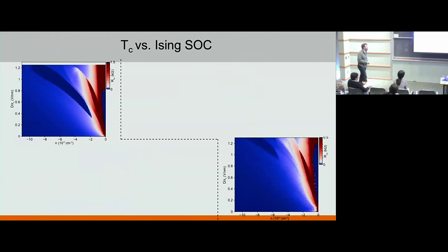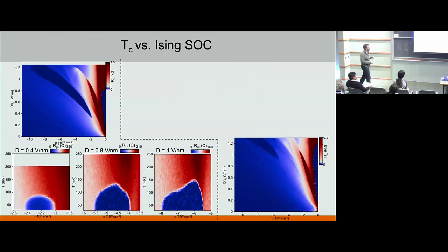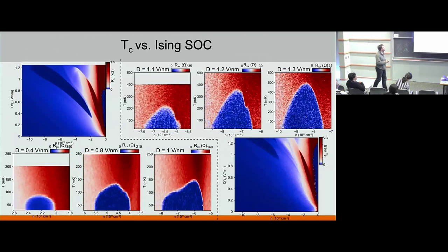And just to give you a few examples of how the TC evolves with doping. If you have small Ising of 0.4 meV, the pockets emerge fairly quickly. So at 0.4 volts per nanometer, you already have superconductivity. But the main point is that the superconductivity saturates and the TC is essentially stuck at maybe 150 millikelvin, okay? If you do the same experiment for the large spin-orbit coupling case, you have to crank up the displacement field much higher. But as a consequence, you are getting TC that is much higher, by a factor of 3 or more.